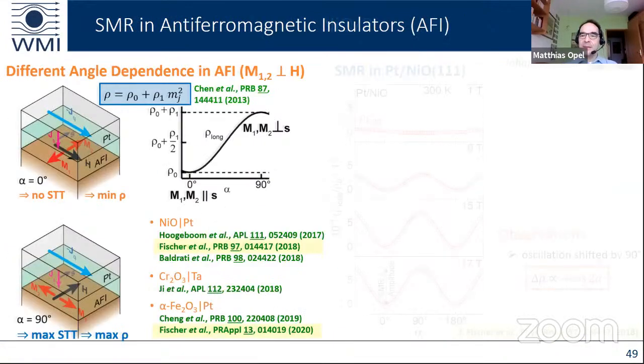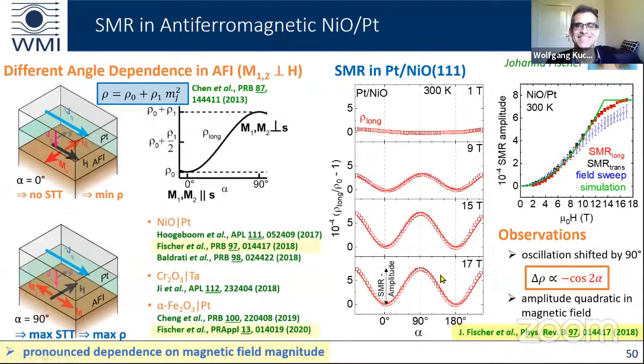Sorry for that. Leads to the oscillation of the SMR amplitude. And the higher we take the field magnitude, so when we apply a magnetic field of 17 Tesla, then we have just one single domain and we can rotate the single domain. Therefore, we get a very high SMR amplitude. When we have lower magnetic field, we have a mixture of three domains, and therefore the magnitude of the SMR